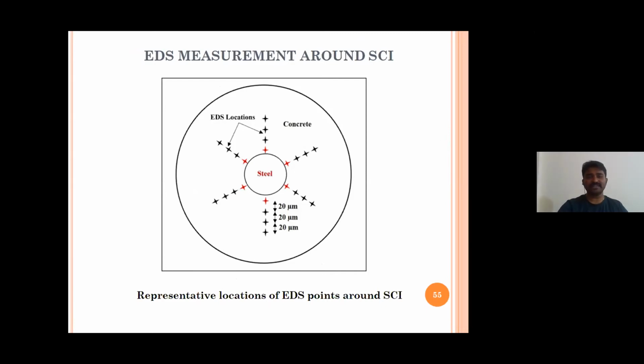Once the porous zone thickness is done, that is the first engineering property that I was trying to study. The next engineering property was hydration product. What are the hydration products which are forming at the steel concrete interface? We are very curious about what kind of hydration product. Usually the hydration product is CSH, there is calcium hydroxide, some voids, right? So these are the three major parts of hydration product. We were curious to know what kind of hydration product is formed at the interface.